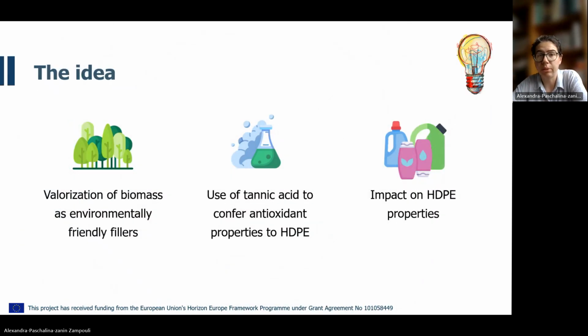In the context of REDONDO, the general idea is to valorize biomass to produce environmentally friendly fillers. So we have had the examples of lignin and cellulose earlier. And here at AUTH, we used tannic acid to confer antioxidant properties to high-density polyethylene. And beside the antioxidant potential, we further examined the impact of tannic acid on the other properties of HDPE.